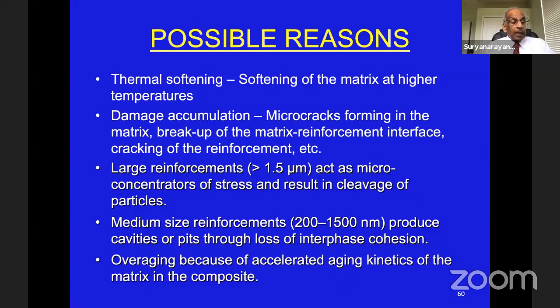But the more important thing, why we were able to get this particular situation, is because the overaging of the matrix takes place, because aluminum 7075 is an age hardenable alloy. Overaging takes place. The reason being there is a lot of difference between the coefficient of thermal expansion of the reinforcement and the matrix that causes stresses. Those stresses cause generation of dislocations. Those dislocations act as heterogeneous nucleation sites for the formation of a precipitate, and that accelerates the process, and that's why that's responsible.